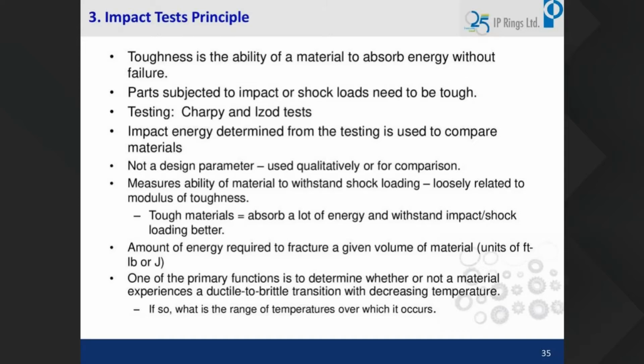We have made many studies. In heat treatment, each supplier has his own oils developed by him. In some of the oils we won't get the required impact. If we go for salt bath, the impact will be slightly lower compared to the oil we are using. By this we can judge where we have to use salt, where we have to use oil, or how to improve the mechanical properties in salt. In that case we slightly tinker with the hardenability elements like molybdenum, chromium or manganese to achieve the property required in oil.